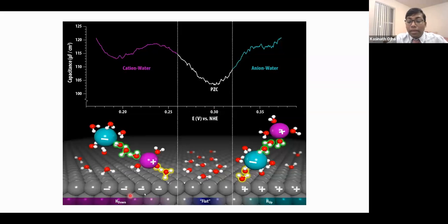So if you have a negative charge on the surface, let's say on platinum, then you have solvent molecules, particularly here water, with hydrogen towards the surface. And once hydrogen is towards the surface, oxygen is upward, then this attracts cations to come closer. And that leads to a change in the capacitance curve. Once the cation goes closer to the surface, it leads to an increase in the capacitance. So that leads to a peak.